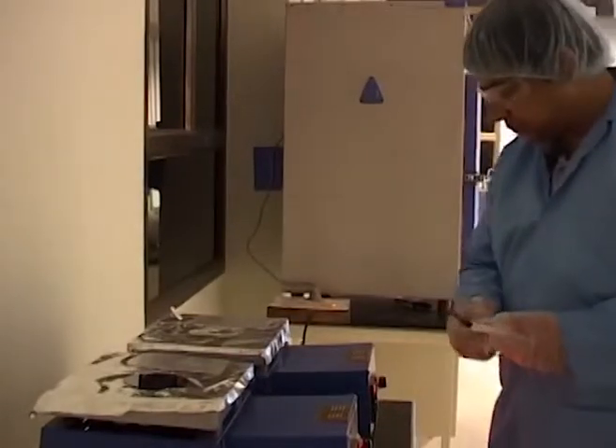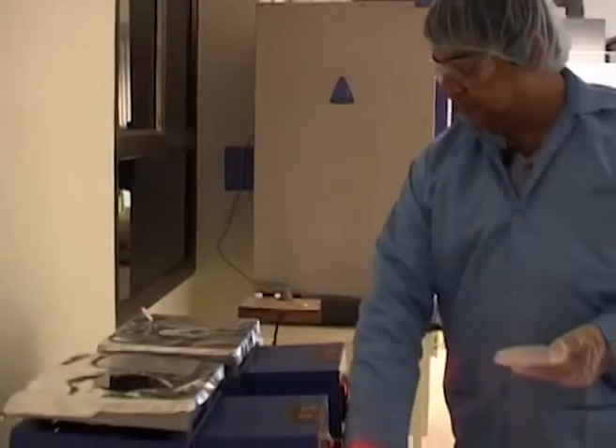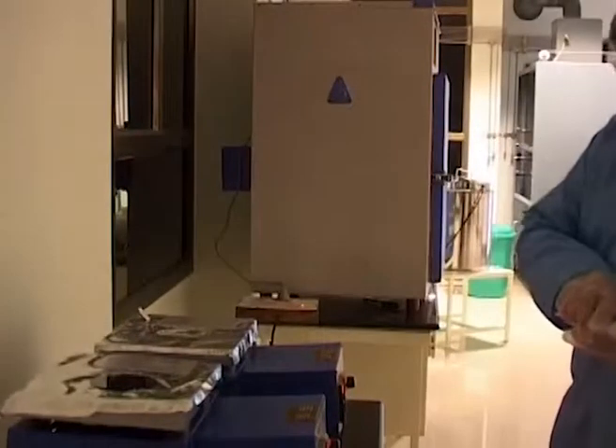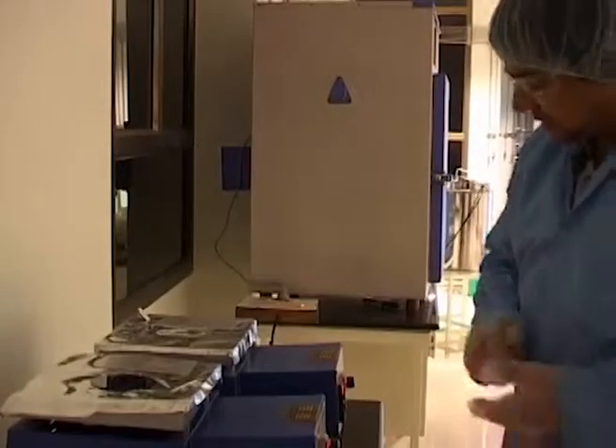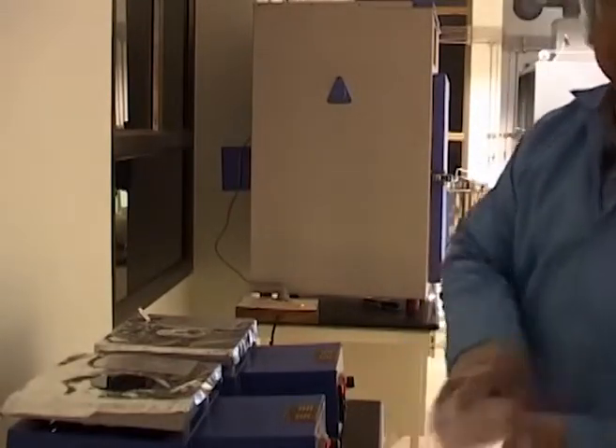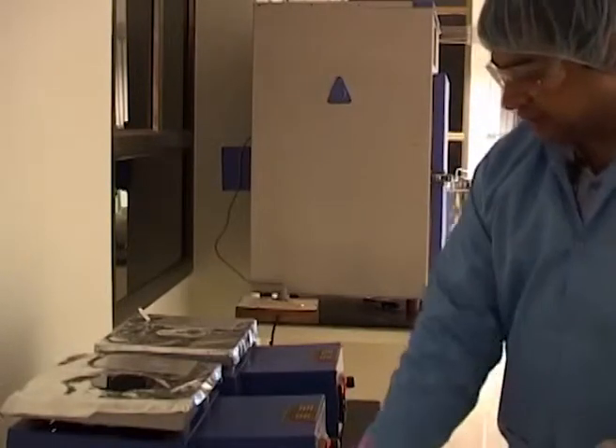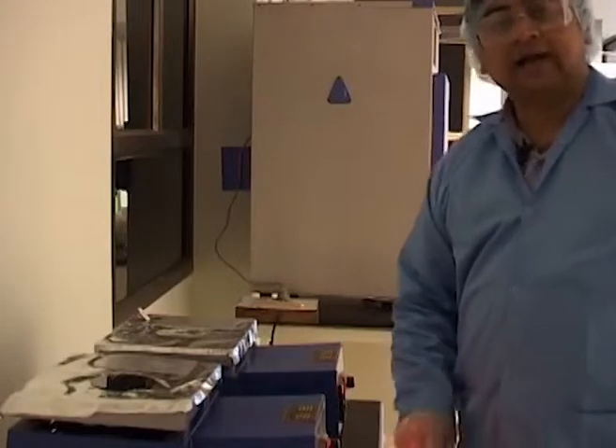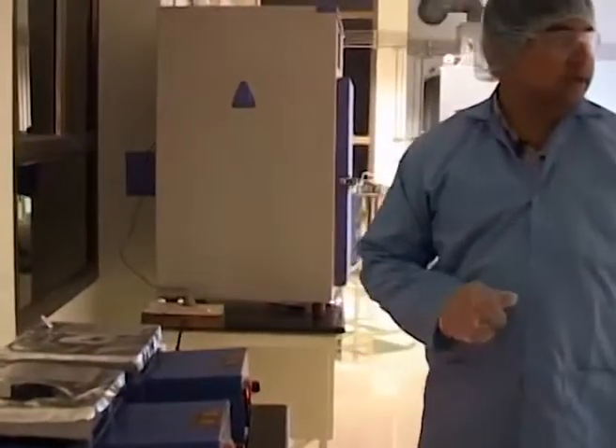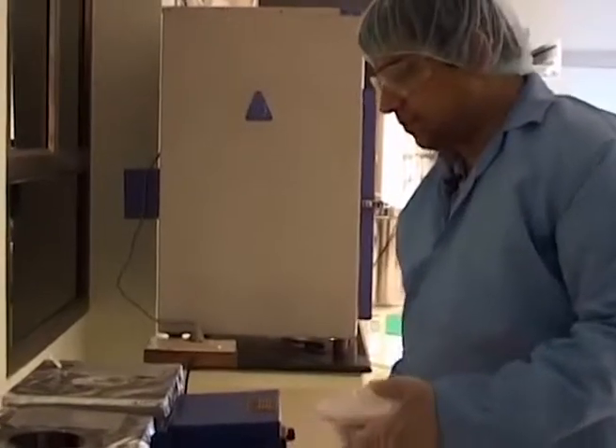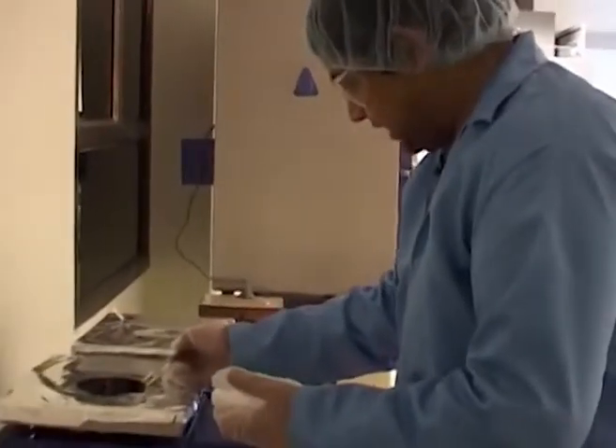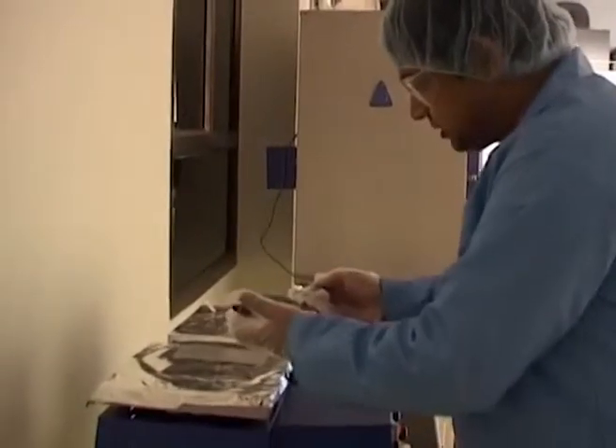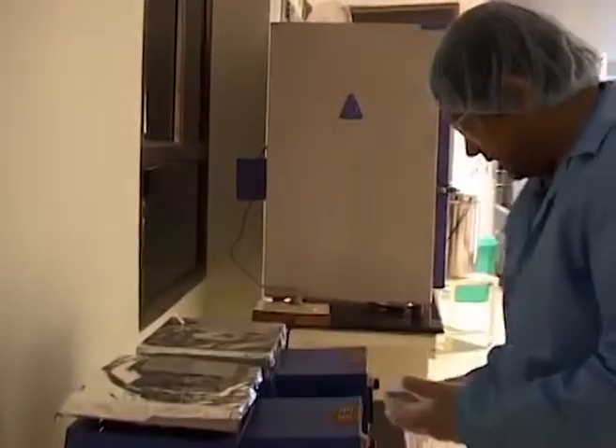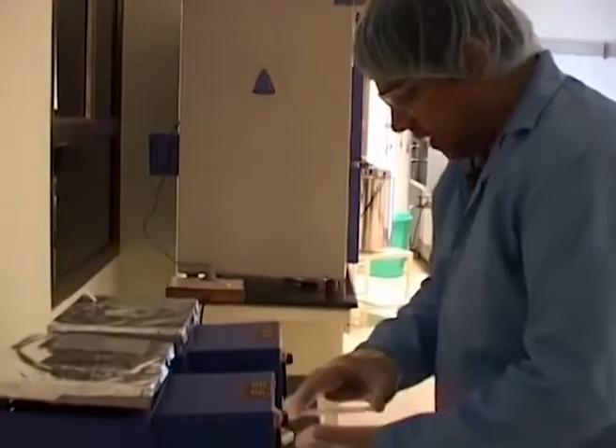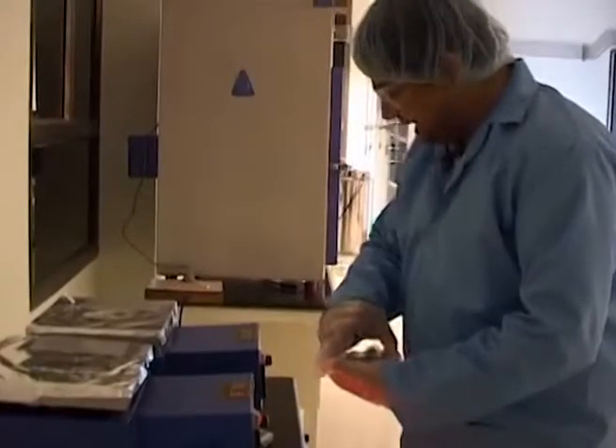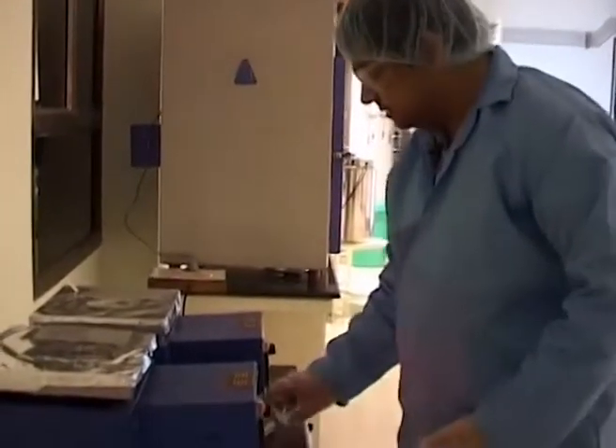We turn on the stop clock and wait for the alarm bell to go off so that we know that we have heated for the time cycle that was supposed to be. Again, we have to equilibrate it to room temperature and then put it back into the 95 degree step so that we can have a properly exposed and cured photoresist film. So time is up now, and we take it back, put it back into its resting place, wait until this equilibrates to room temperature, and then go back and do a 6 minutes heating step in the next temperature step, that is 95 degrees Celsius.